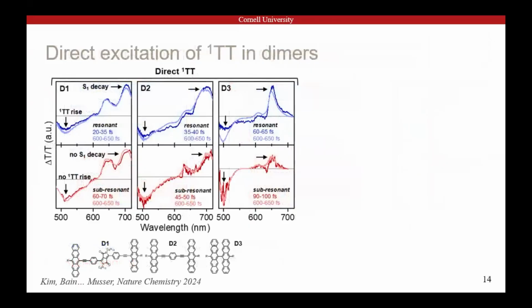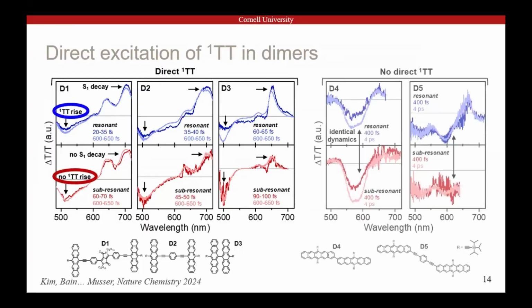We can use this same approach to study all of our dimers. These three show the same basic behavior. You pump in the blue resonantly. You have a distinct rise of the triplet pair signature, decay of singlet fingerprints. When you pump in the red, all you see is the triplet pair state on the earliest time scales that you can capture. But it doesn't always work. Oh, yes. It doesn't always work. In these two dimers, no matter where we photoexcite, we see the same behavior of singlet slowly-ish turning into triplet pairs from picosecond to many picoseconds time scale.